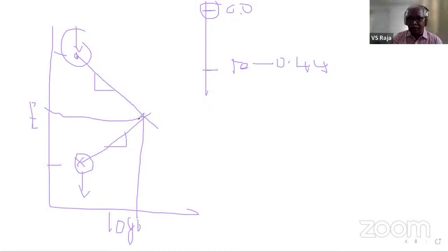Okay, it's good. Now let me go to high temperature. In high temperature, oxidation is slightly different from that of aqueous corrosion. Even in aqueous corrosion, for example, iron can get corroded and finally it can form hematite, or it can form magnetite. But the difference is iron will corrode and form iron hydroxide. Iron hydroxide will convert into ferric hydroxide. Ferric hydroxide will dehydrate and can form hematite, or magnetite can form. So the oxide formation in aqueous corrosion is through formation of hydroxide and things like that, and then forms oxide. But in the case of high temperature oxidation, what happens?